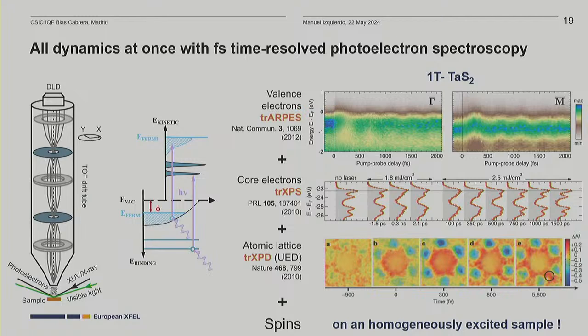And you could also do time-resolved photoelectron diffraction, and from there you should be able to understand how the lattice changes at the same time as the electrons, the chemistry, the spin changes. Note that this example is not from photoelectron diffraction in forward scattering, that has not yet been realized. So this comes from ultrafast electron diffraction, but one would expect something like this. So this is an example on this material.